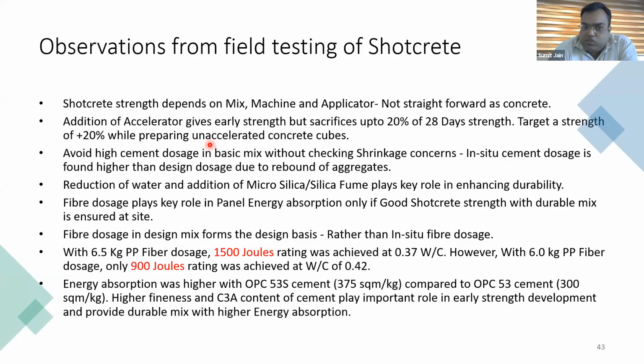Then we can definitely reduce the water, and adding microsilica, silica fumes, enhances the durability, which we have seen. And the fiber dosage plays a very key role in panel energy absorption. The higher the dosage, the better the absorption energy you will get. But please keep in mind that good Shotcrete strength and a durable mix are a must for this rule to be acceptable. Otherwise, if you don't have a good strength Shotcrete, if you don't have a durable mix, even adding fibers will not help you. So these are the prerequisites for good energy absorption in the panel.